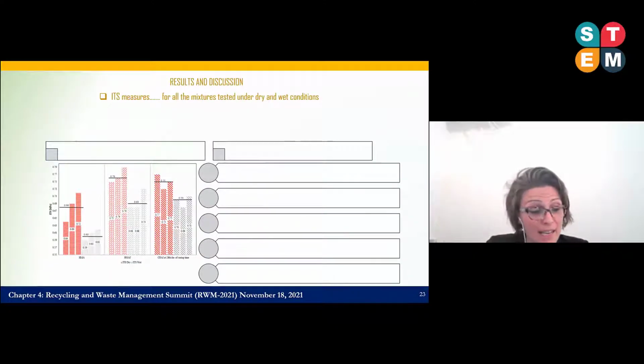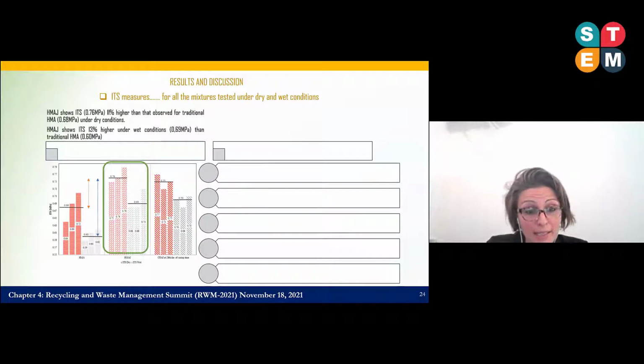Summing up the ITS for all mixtures, we can see that under dry conditions, in the red color in the graph, the innovative hot asphalt mixture shows a mean ITS value almost 8% higher than the observed value for the examined traditional hot mix asphalt, and almost 12% higher under wet conditions than the traditional one.